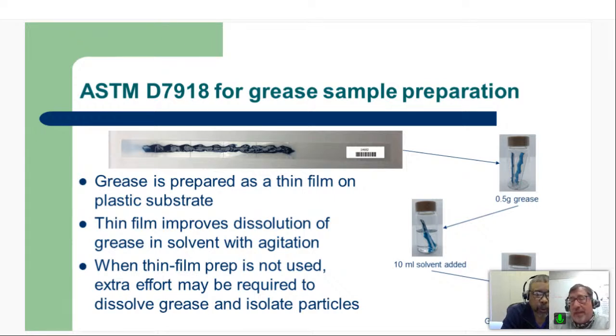And we have found that it works in the same way as the glass beads and the things that were done way back to try to get more thorough liquefaction, if you will, of the thickener, basically getting the thickener out of the way. Some of that is enhanced now by this thin film process, where the solvent can do a better job in agitation on the surface to break that down. And we've seen some good results with that. So the grease is on the thin film. That provides the better dissolution and agitation.